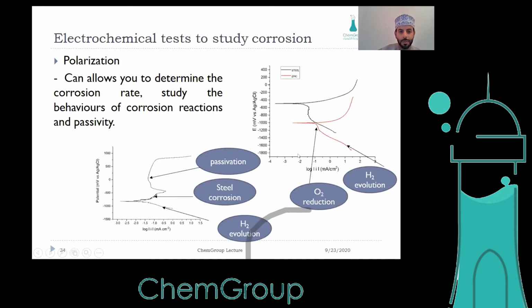Then we have the polarization, which is one of the main or the most important experiments, which allows you to determine the corrosion rate, and study the behaviors of corrosion reactions and passivity. For example, if I did this myself, which is a steel in carbonate solution, you can see here where the cathodic reaction is, whether it's oxygen reduction or hydrogen evolution. Hydrogen evolution is normally flat, but oxygen reduction is normally vertical. So you can see whether the reduction reaction is oxygen reduction or hydrogen evolution. And then you can see the steel corrosion or the metal corrosion. And if there is passivity, you can see it clearly in this polarization test.